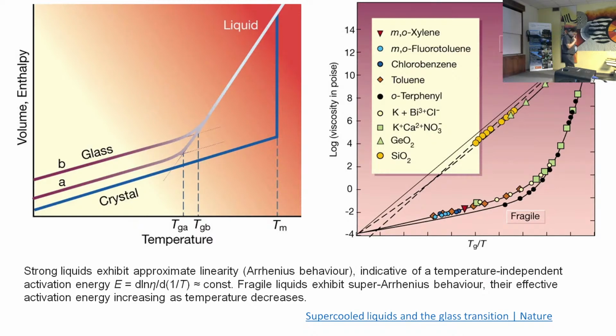Now, you have glass made of fused silica, which is in all our windows, and if you determine the viscosity as a function of temperature, you get this Arrhenius plot, which means that viscosity decreases in a very smooth way. And this has very big advantages in terms of glass technology. It's much easier to mold the glass. You can make sculptures with glass, whatever you want with glass.